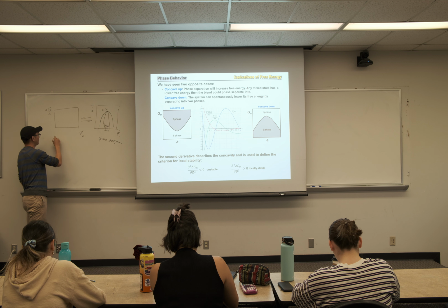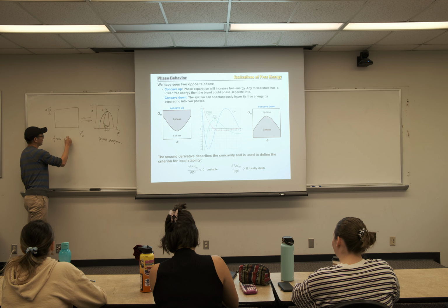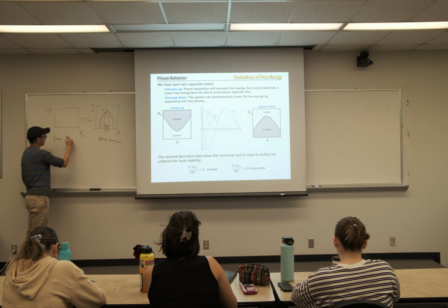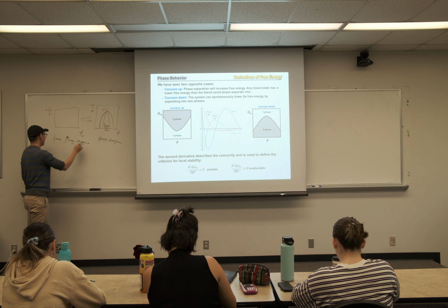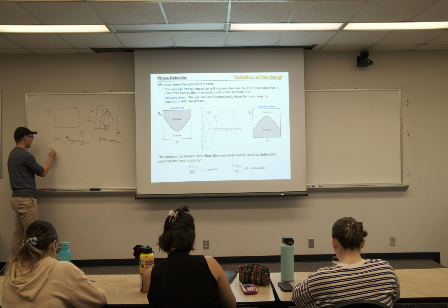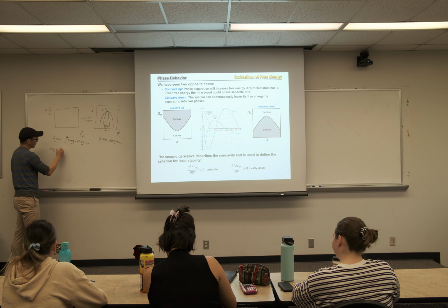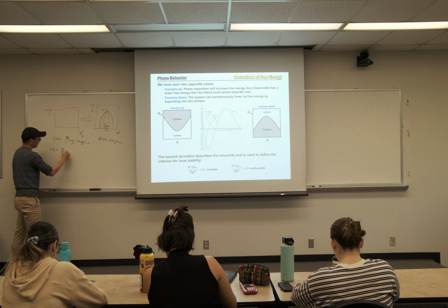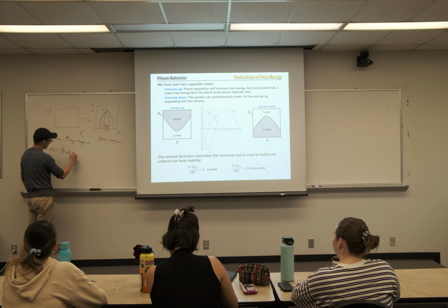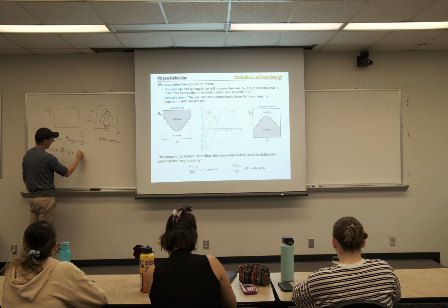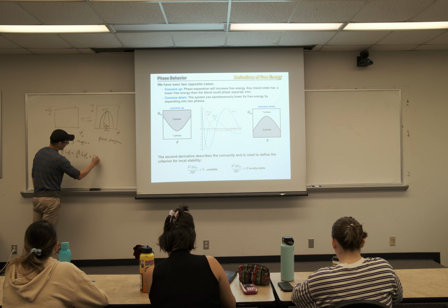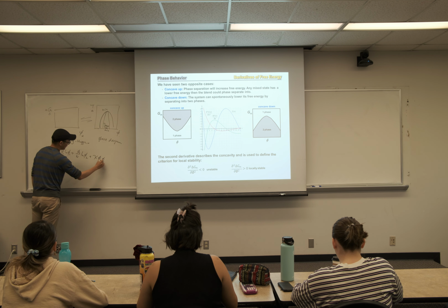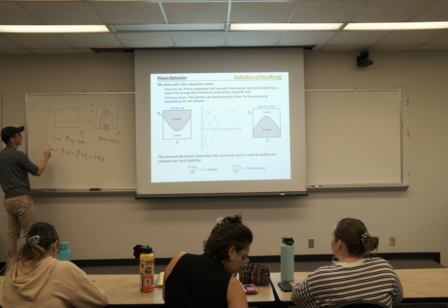This is from Flory-Huggins theory. We talked quite a bit about this equation. Delta G is related to phi 1 log phi 1, plus phi 2 divided by n times log phi 2, plus chi times phi 1 phi 2, right? So this will tell you this graph.